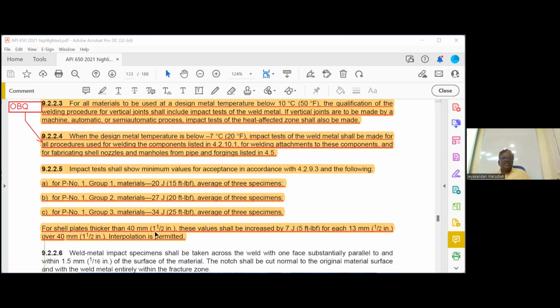For plates thicker than 40 mm, 1.5 inch, this value shall be increased by 5 foot-pounds for every half an inch. Interpolation is allowed for averaging. For example, if we take P1 group 1, what is the average required? 15 foot-pounds. This is applicable only when the thickness is 1.5 inch or less. Suppose your thickness is 2 inch. So for every half an inch, how much do you have to increase? 5. So 15 plus 5, that should be 20 foot-pounds value you have to get. That is the meaning of this.